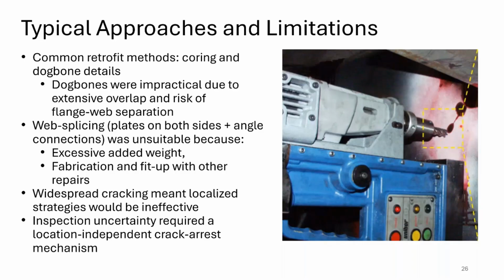If you don't know where the location of the crack is, you typically do a dog bone detail, which is basically two coring holes joined by a slit, with the intention of intersecting the crack as it propagates. As we had so many indications, these were basically unfeasible. We would have had to put dog bone details throughout the length of the girder, and that would have made the bottom flange, or the tension flanges, completely separated from the web.